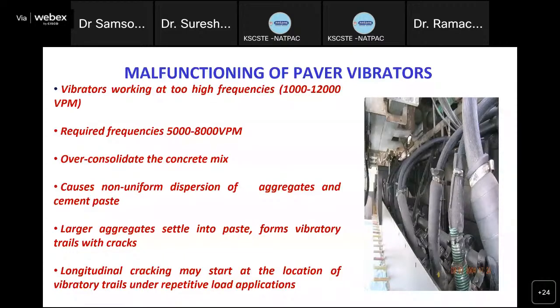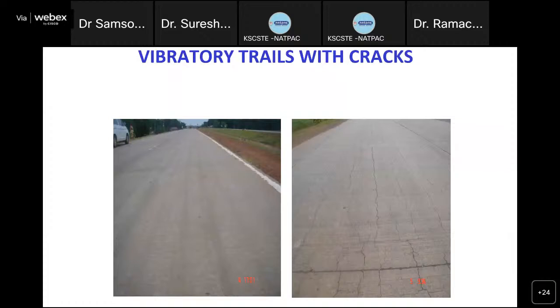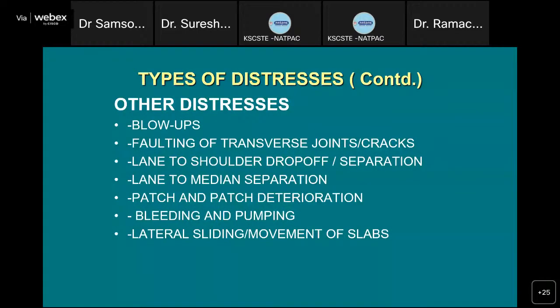Normally, the frequency of the vibrator should be around 5,000 to 8,000 vibrations per minute. Now, if the vibrations are too high, of the order of 10,000 to 12,000 vibrations per minute, then it will result in this kind of cracks. It causes non-uniform dispersion of aggregates. There is too much vibration, and aggregates and cement paste get segregated, and that leads to this kind of vibratory cracks. Therefore, we must take precaution when doing concreting. We must ensure that the vibrations of the vibrators are within the specified range of 5,000 to 8,000 vibrations per minute.